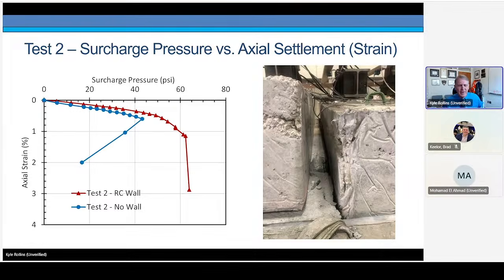And there's quite a bit of difference that you can see between the behavior with the reinforced concrete wall in place and without it. With the wall in place, we have fairly ductile load versus settlement, load versus strain curves. Whereas with no wall, we're getting a rapid decrease as we get to kind of a catastrophic failure where the wall just slides into the surrounding soil, right?